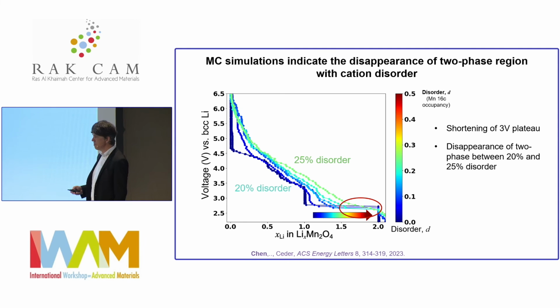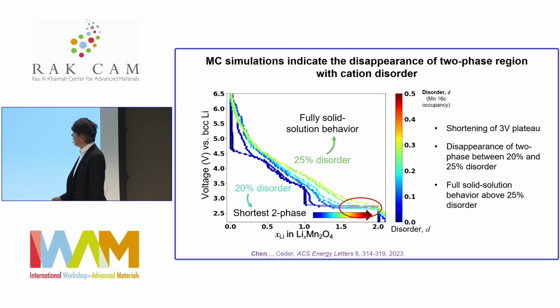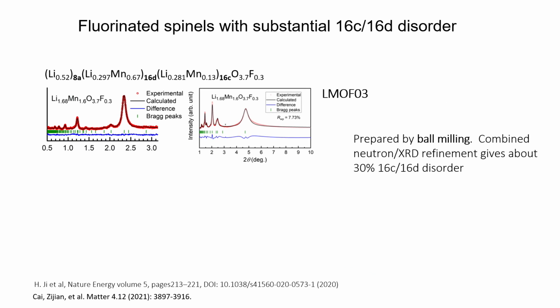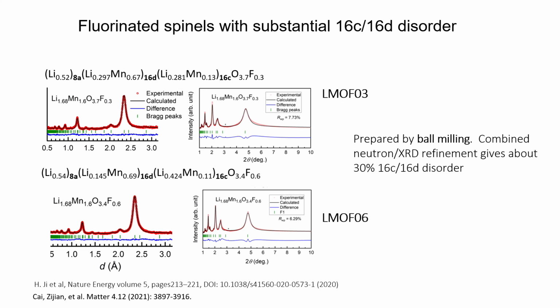So the question is, can you make this material? Okay. Well, it turns out you can by heavy ball milling. If you do heavy ball milling, you can make these unusual spinels, which are neither stoichiometric nor fully ordered. So this is a spinel that's only partially occupied on the 8A site, has almost full occupancy on 16D, the normally occupied spinel, but also has occupancy on 16C. So this was both X-ray and neutron refined. And you can make multiple versions of that. This is versions with different amount of fluorine.